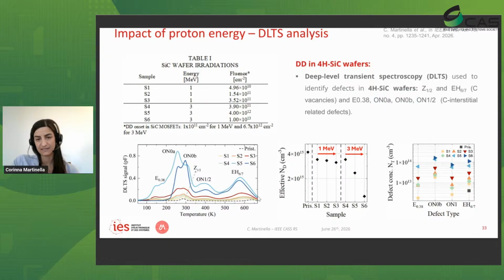Now we analyzed the results. We looked at the effective carrier density in the device after irradiation. Here we report the results for each of them in comparison with the pristine. We can see that with higher fluence, the effective carrier density tends to decrease, of course. And then we also extracted the defect concentration within the device. So all the details are reported in the paper above. But in general, we observed the presence of electrically active defects that were related to carbon vacancies and carbon interstitials.